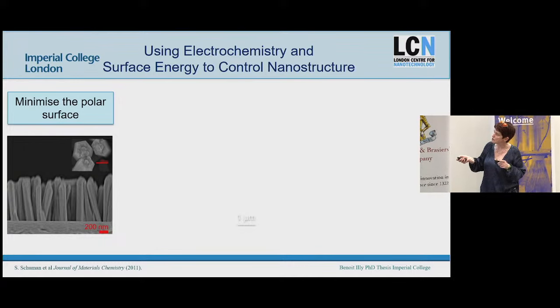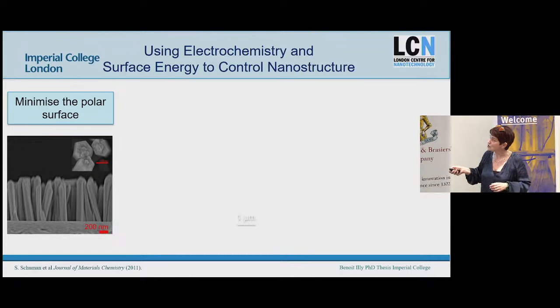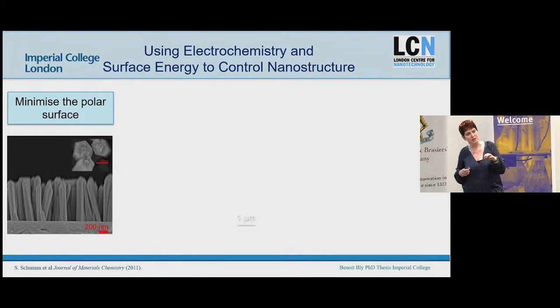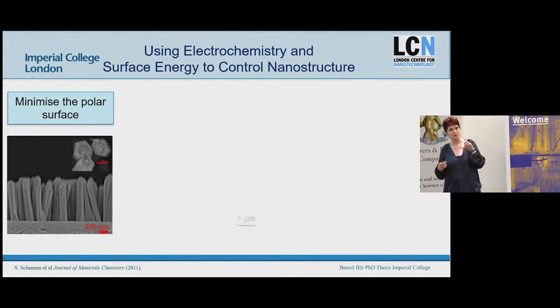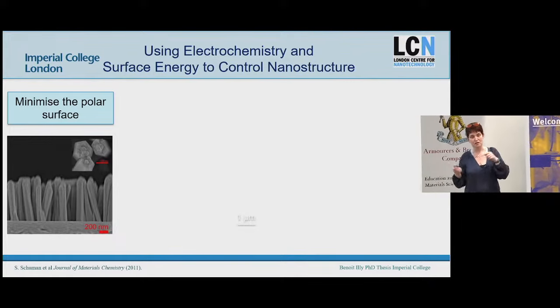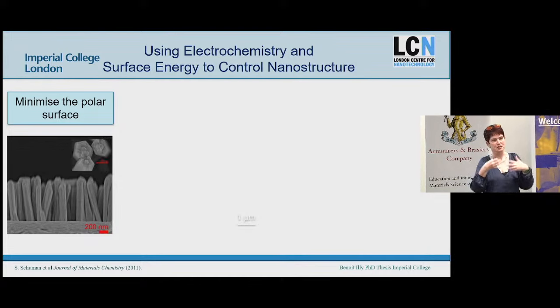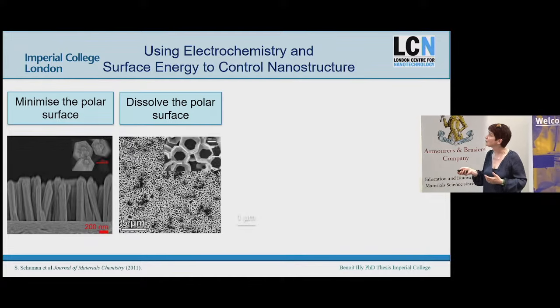These are about 50 nanometers in diameter. They grow straight up. They grow aligned because the crystal geometry is determining the growth. And this direction also happens to be the optimum electronic conduction direction. So you're growing very preferentially conducting nanostructures that align. So these are really interesting for interdigitating electronics, for example.